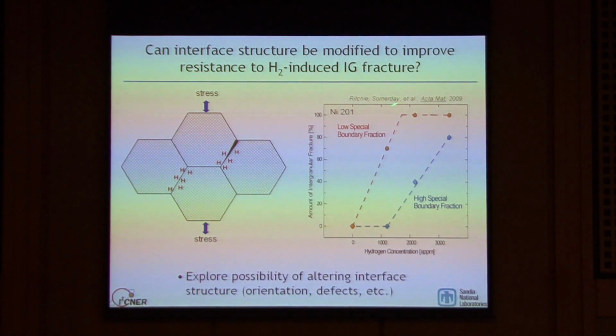What we did is look at just a nickel 201. Our colleague at Lawrence Livermore was able to process this nickel 201 to change the grain boundary structure, basically changing the atomic registry of certain grain boundaries. Materials with high atomic registry across the grain boundaries we call high special boundary fraction, and low special boundary fraction has grain boundaries that don't have as much atomic registry.